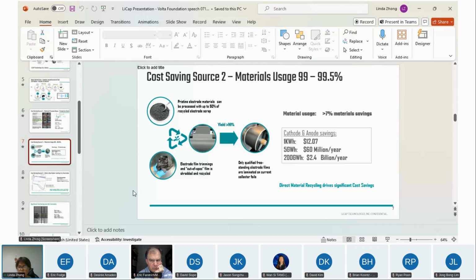If your electrode has some kind of defects, for example, surface defects, like cracks, you can do 100% direct recycling right there. In our process, you can vacuum it up, go back to the powder room, and chop it up to the powder state. You can reuse it just like a new material. So you only have yield loss after the lamination.